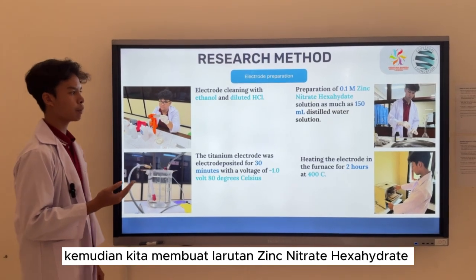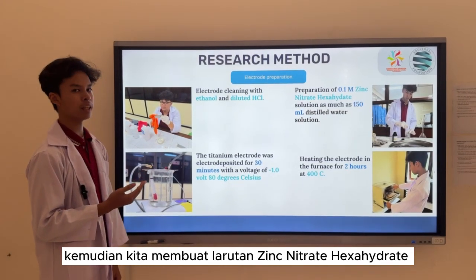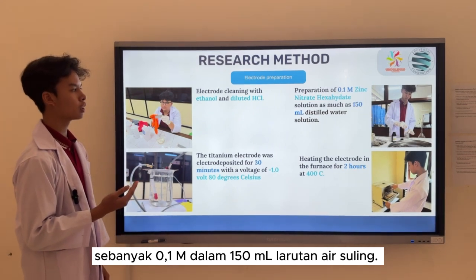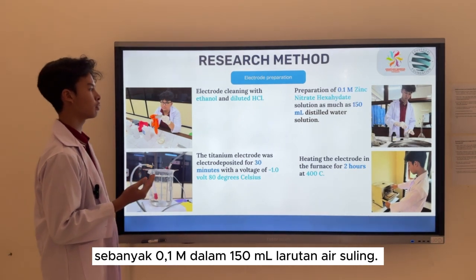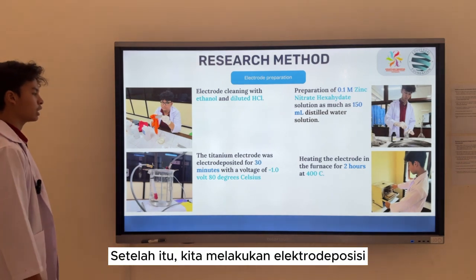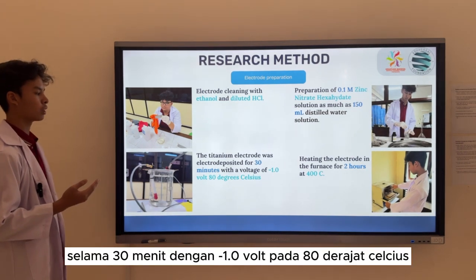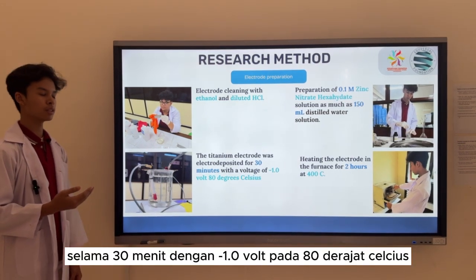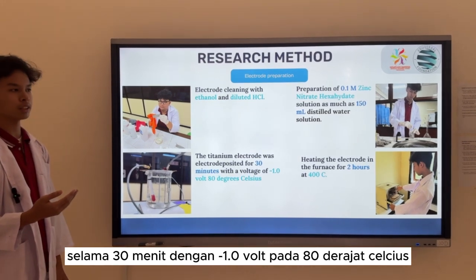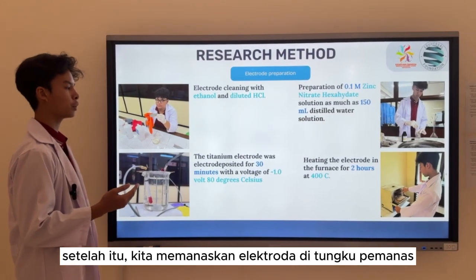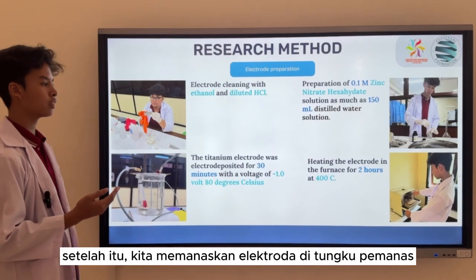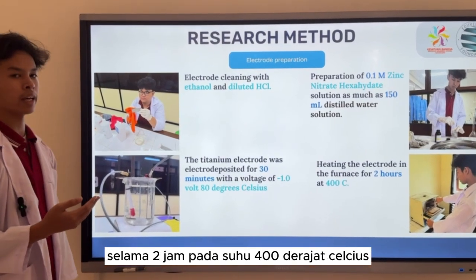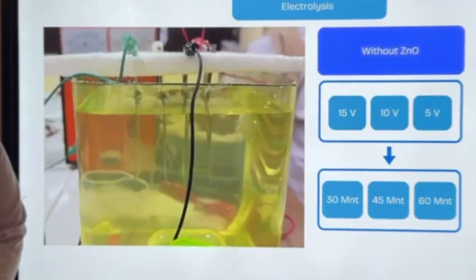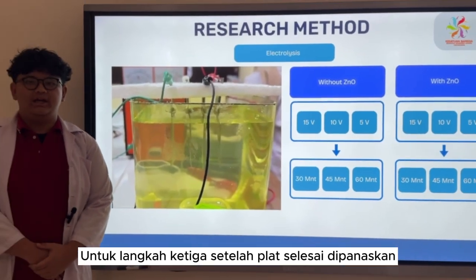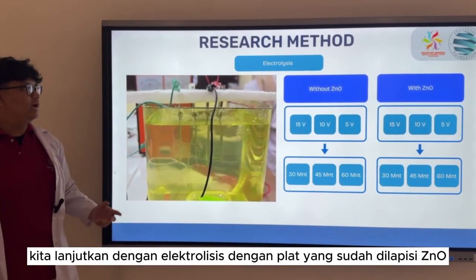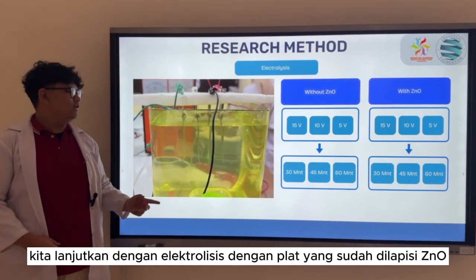And then, we are making a solution of zinc nitrate hexahydrate as much as 0.1 mol in 150 ml distilled water solution. After that, we are doing electrode deposition for 30 minutes with a voltage of minus 1.0 volt, 80 degrees Celsius. After that, we are putting the deposited electrode into the furnace for 2 hours at 400 degrees Celsius.